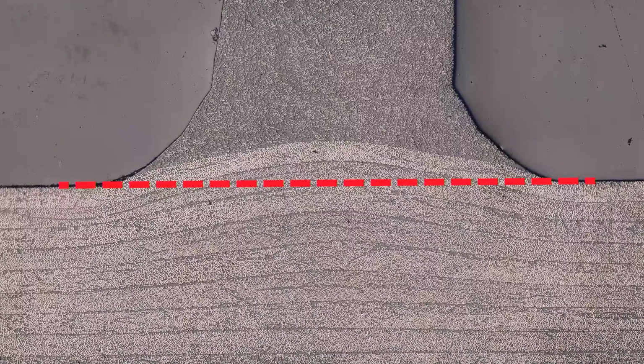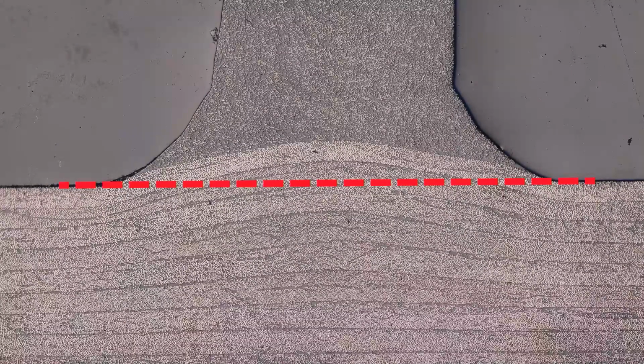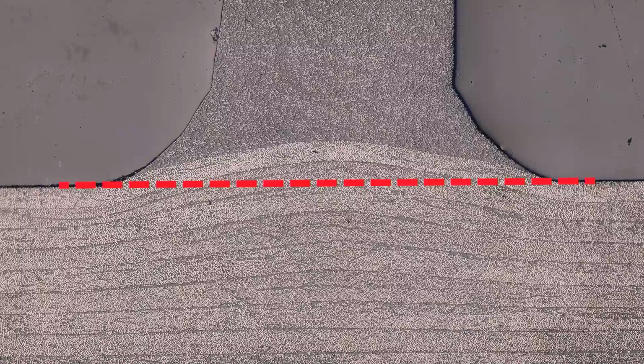What you see here is, on the top, the injection molded compound, and on the bottom, fibers. So what's happening here is that the fibers from the laminate are partially within the injection molded cavity. And this is what we're calling fiber migration.